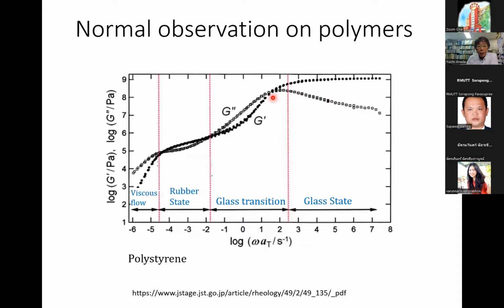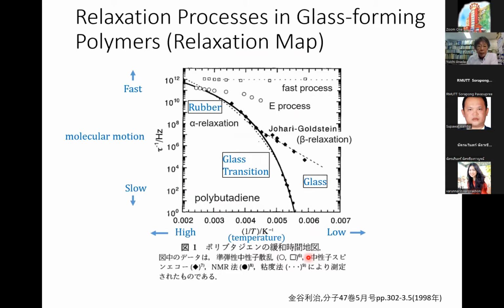The peak position of frequency depends on temperature. So this peak moves if we observe at a different temperature. So the relaxation map shows the total image of temperature and relaxation time or frequency. This is a very important map to characterize physical properties of polymers.